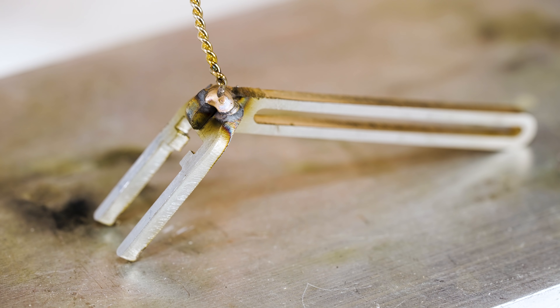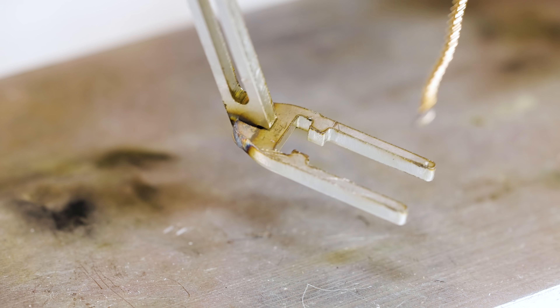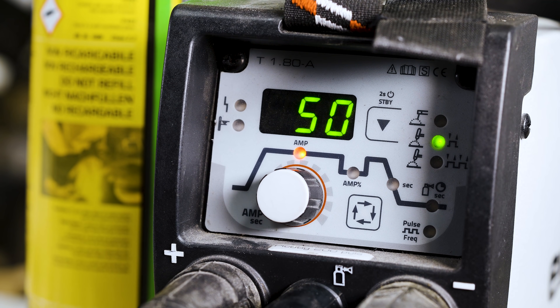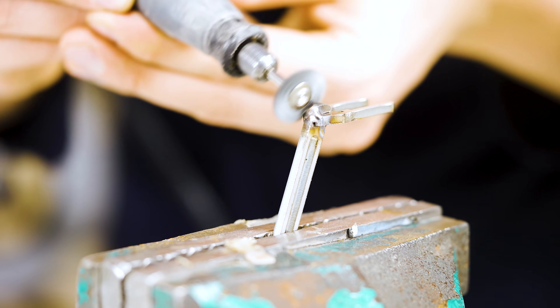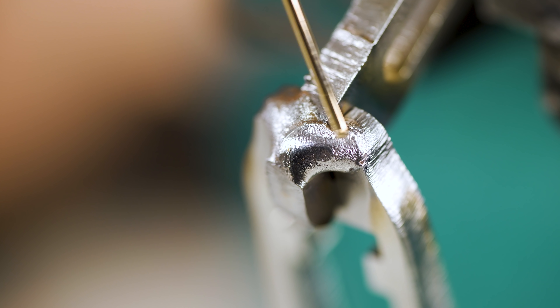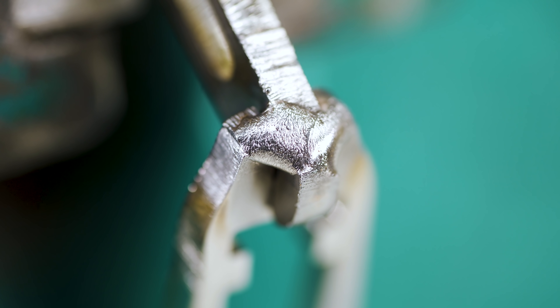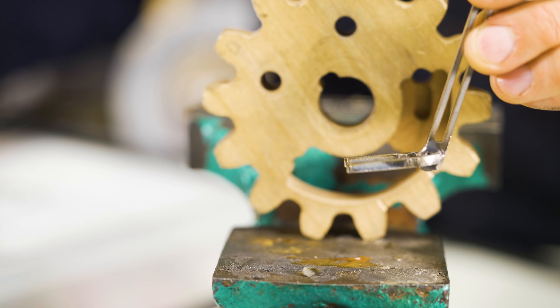I put one tack right here on one side, then turn to the other side. I'm going to do a third one here — probably completely unnecessary but the marbles will go there, so why not? I'll do it a little bit colder, at 50. Here you can see the nice fillet — it goes smooth to this surface and comes down to the other part. That looks really nice. On the back side you can see the same kind of thing. Here are the two welds from the back side going into each other, then from the other side. I didn't clean the metal before — the parts are pretty clean so it seems okay. I'll trust this as a dropper.